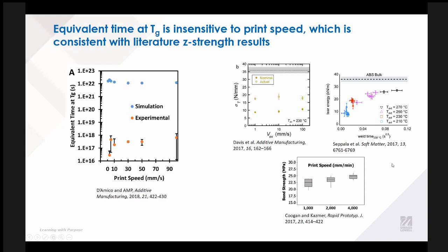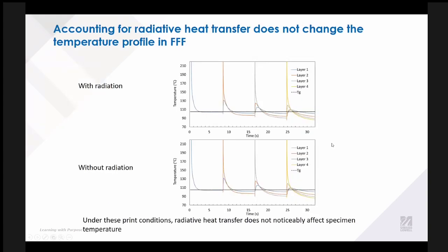So that's kind of an interesting thing, and kind of nice, because it means that in terms of strength, you can just print faster. You do need to then be more concerned about your resolution, but in terms of strength, that's a variable that isn't as sensitive. I did mention that we don't account for radiative heat transfer in FFF, and that's just